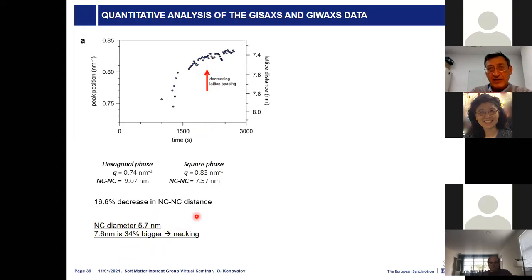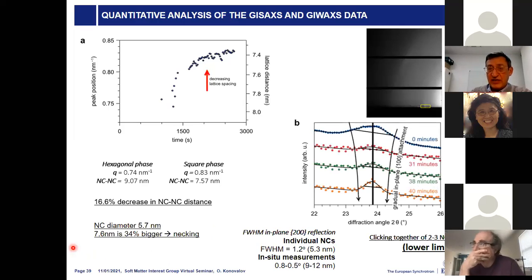But anyway, the particles are well oriented and they scatter like a single crystal. It means that the atomic planes between neighboring nanoparticles are coherently aligned on the atomic scale to be able to scatter like a single crystal. So why did this happen? We saw that it could be the idea that there is necking, so the shape of the particles remodels, and some atoms go in between these nanoparticles to make a solid interaction and align them atomically.